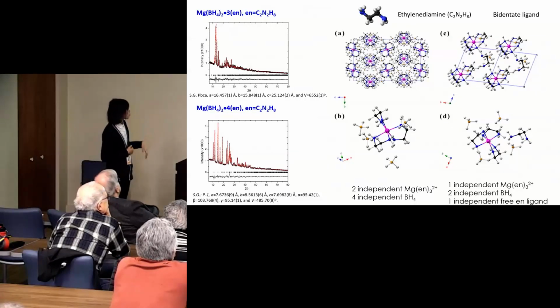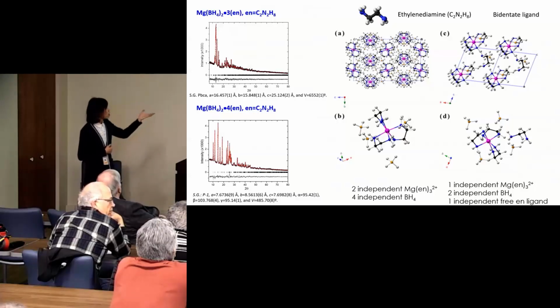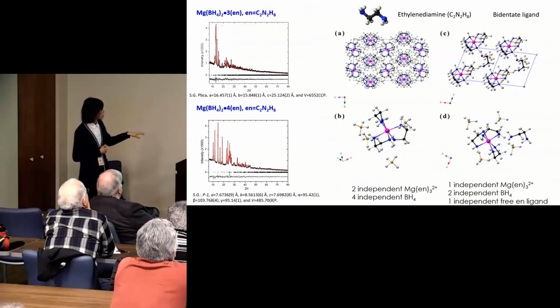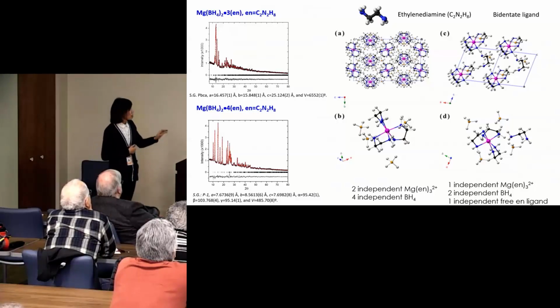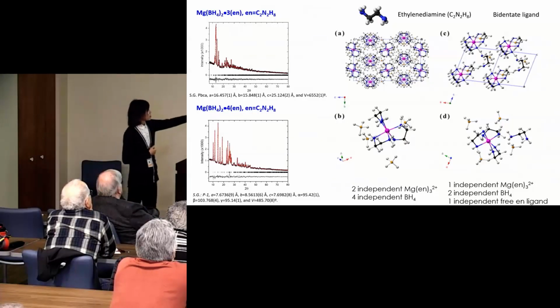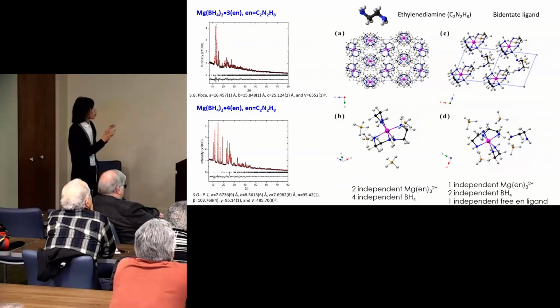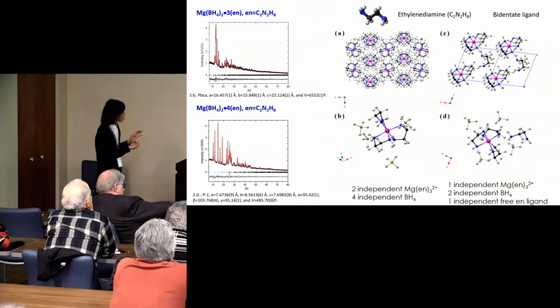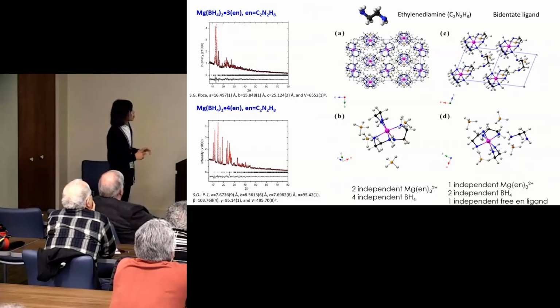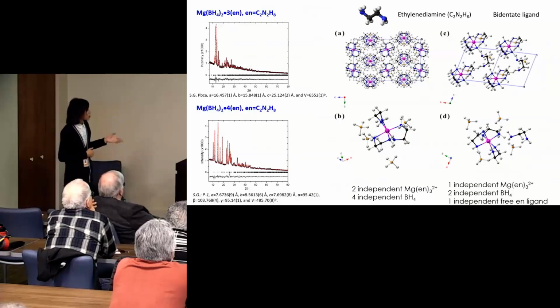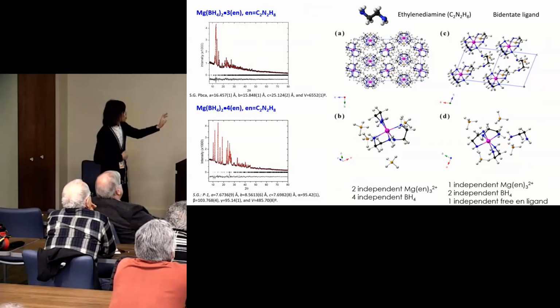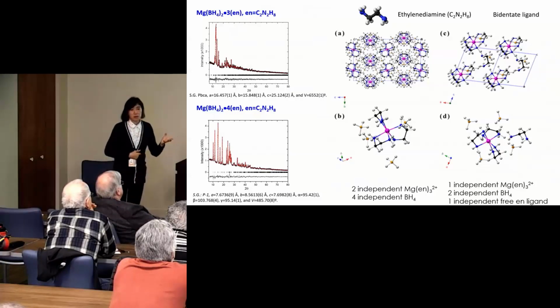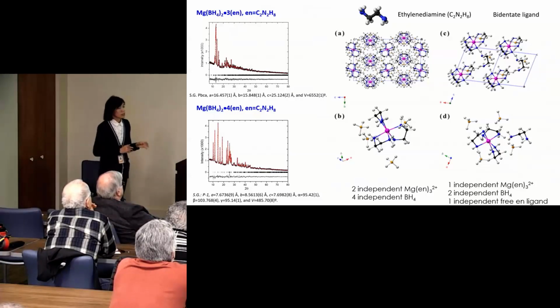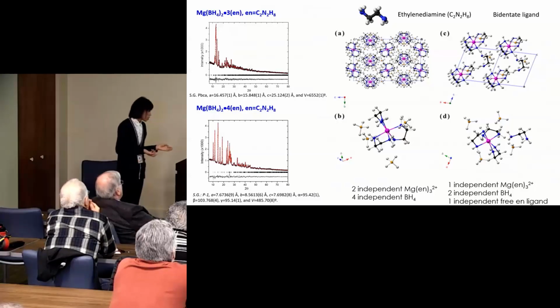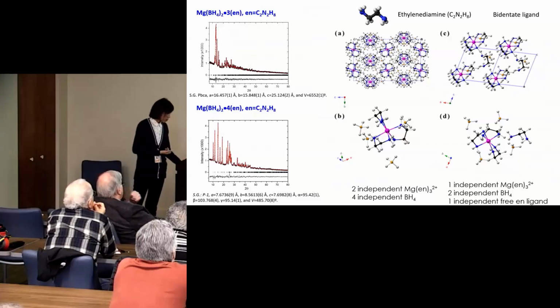as you can see, for example, the tri-ethylenediamine compound forms an orthorhombic structure, which has a large unit cell. The tetra-ethylenediamine compound forms a triclinic structure. So to refine the structure, we see that magnesium will coordinate with 3 ethylenediamine and form this magnesium tri-ethylenediamine complex cation. So again, if you want to refine it, we have to put rigid body constraints on the ligand. With help from GSAS, we were able to refine the structure.